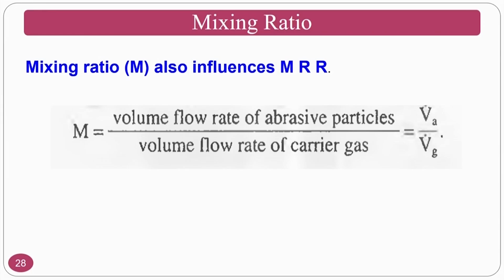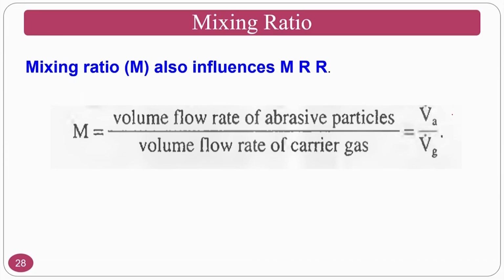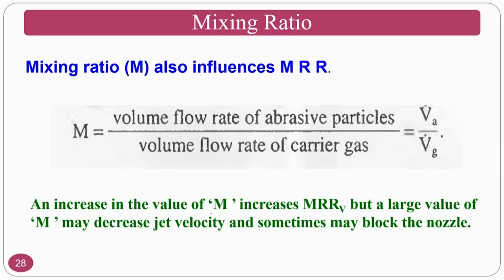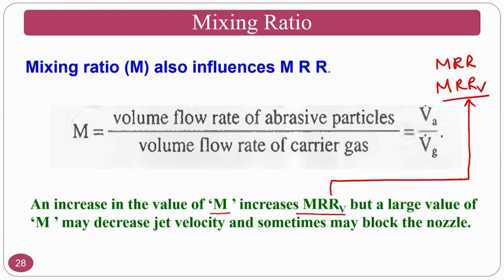Next, the mixing ratio. The other keyword here is the mixing ratio, that is nothing but the volume flow rate of the abrasive particles to the volume flow rate of the carrier gas. That means that you have two things here, one is the gas, another one is the abrasive particles. If the mixing ratio is very high, that means that your abrasives are higher in number compared to your carrier gas. So, an increase in the value of M, that is the mixing ratio, increases the volumetric material removal rate. Normally, some people represent material removal rate as MRR, and MRRV represents the volumetric material removal rate. See here it is shown MRRV, that is nothing but the volumetric material removal rate. But a large value of M may decrease the jet velocity and sometimes it may block the nozzle also.